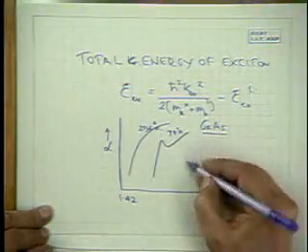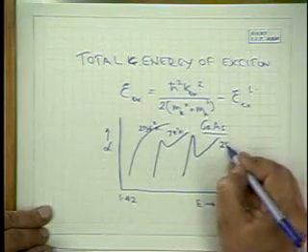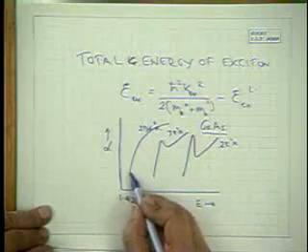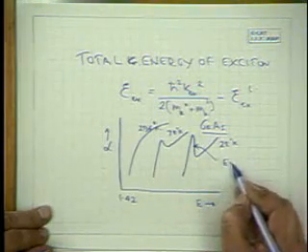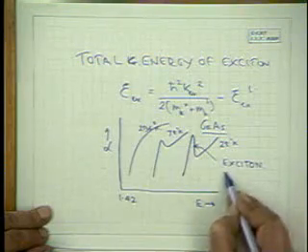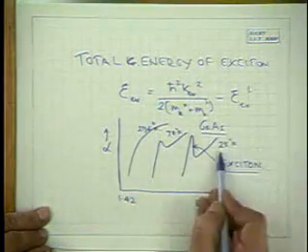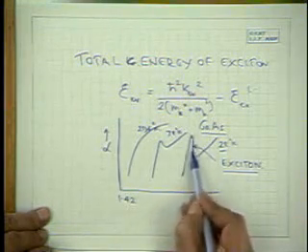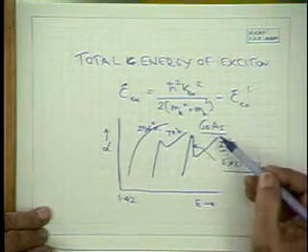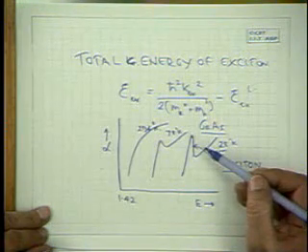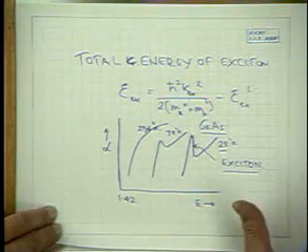And if you go down still further in temperature at 21K, we have a shift in the absorption edge due to increasing band gap, and these features, this peak, is due to the creation of excitons. Notice that the line width decreases as you go down in temperature, and the peak intensity also increases as you go down in temperature. So the observation of excitonic lines is an indication of the purity of a semiconductor, and it occurs when you have extremely high purity semiconductors.